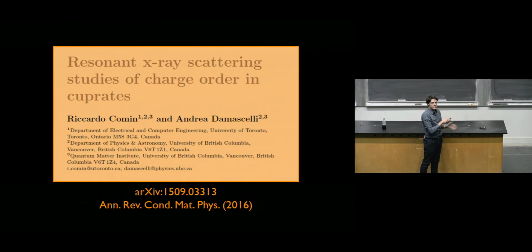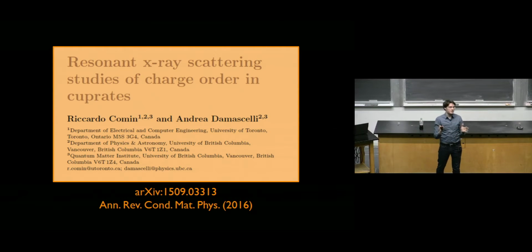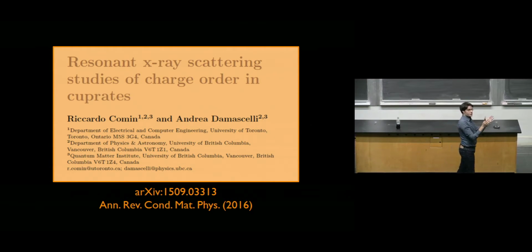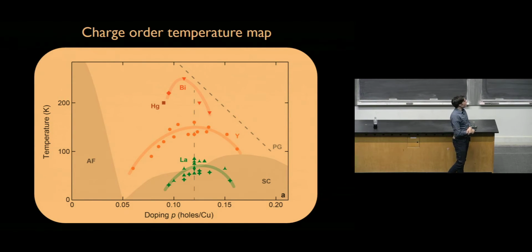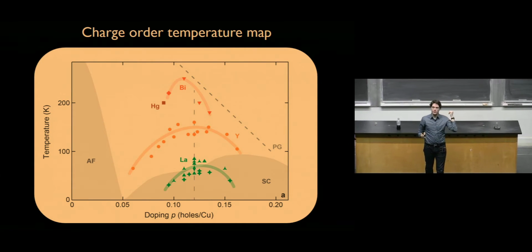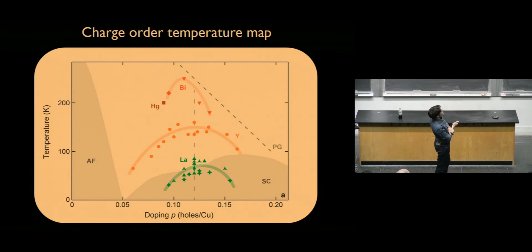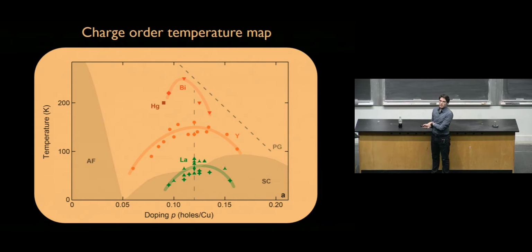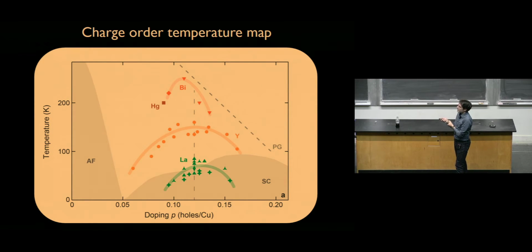So I'm tentatively following the narrative of this paper now in the second part of my talk, where I'm going to discuss specifically the phenomenology of charge order in the cuprates, with an emphasis on the use of resonant X-ray scattering methods to measure this charge order in reciprocal space. And I'll do this in a strange way, in the sense that I'll start from the very end of the story, which is the charge order temperature map as we know it today. So at this point, I think this requires a bit of an explanation of what this is. So this is still a phase diagram in a way. It's not properly a phase diagram because I'm not drawing phases here. What I'm drawing is the onset temperature of charge order, of this electronic crystal state, as a function of doping. So this is a superconducting dome. This is the antiferromagnet. And now we have a new electronic order here in this region between, let's say, 6% and 16, 17%, in all different cuprate compounds. This is really universal.